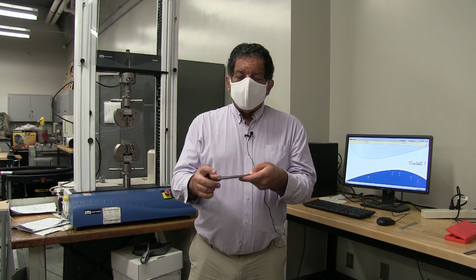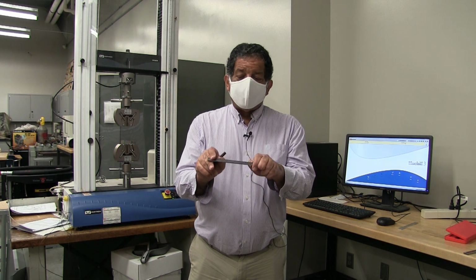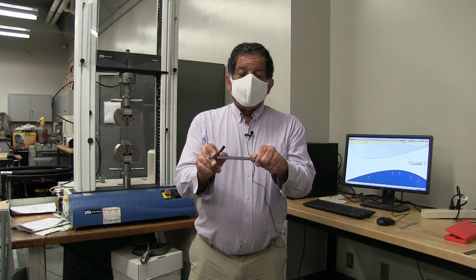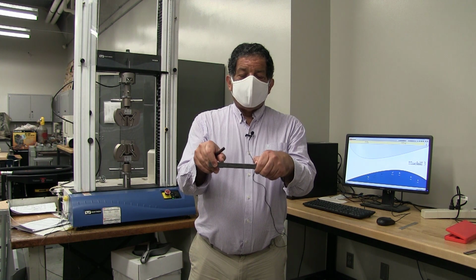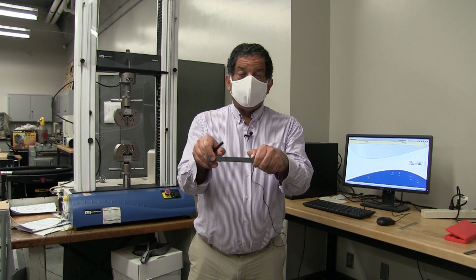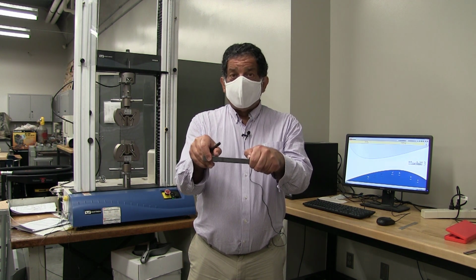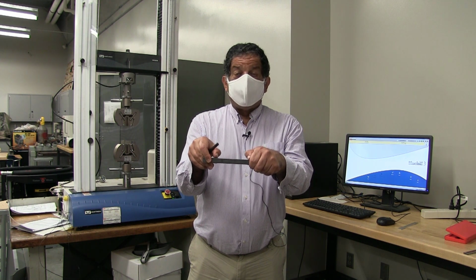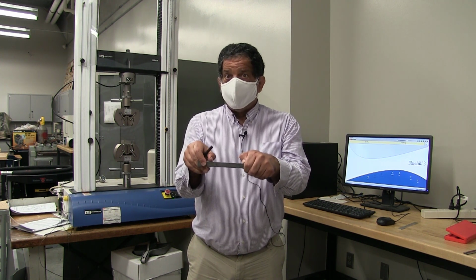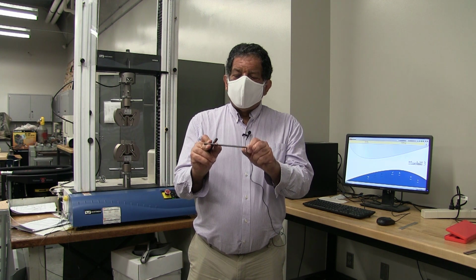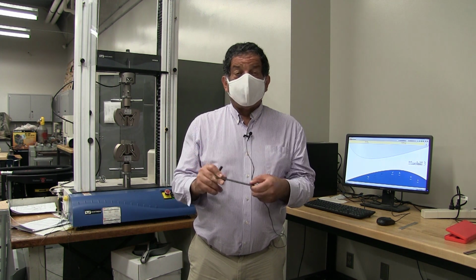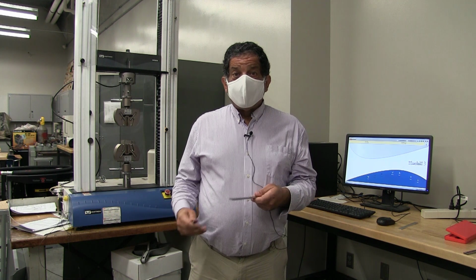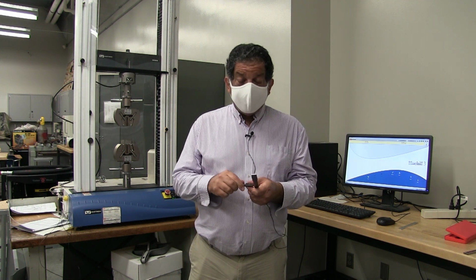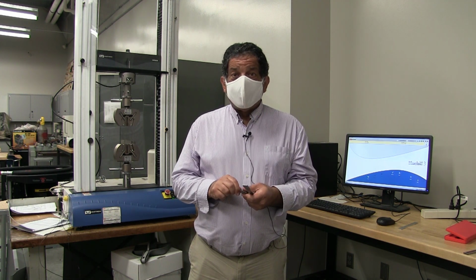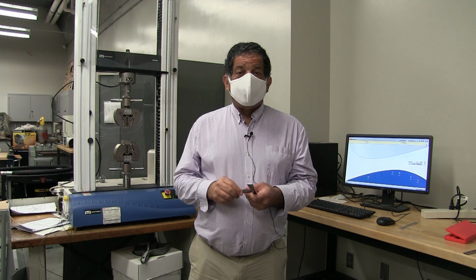In order to do a percent elongation, you could theoretically just reassemble the specimen after it's broken and then say, well, how much did these two fillets, which started out at the initial gauge length of the specimen, how far apart are they now? So you could use that as your final length for a percent elongation calculation. You could also, for a percent elongation calculation, take the final plastic engineering strain and multiply it by 100%. That's an alternative measure of the percent elongation.